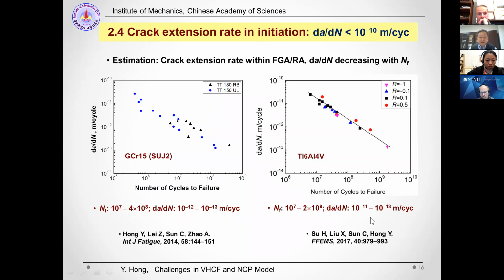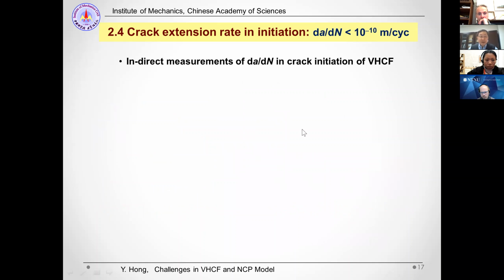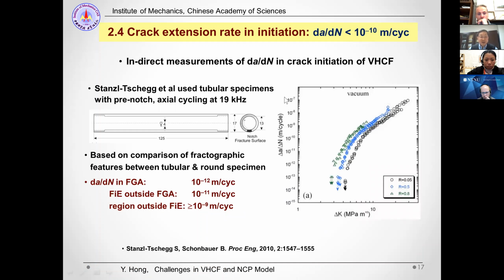It's very slow. And I would like to mention some indirect measurements of these extension rates. This, I think, is the first case, by Stanzl-Tschegg and her co-authors, showing that the extension rate in FGA is 10 to the minus 12 meter per cycle. They use this type of specimen to perform this measurement, and they compare the fracture surface morphology of the tubular specimen and the round specimen to get this value.